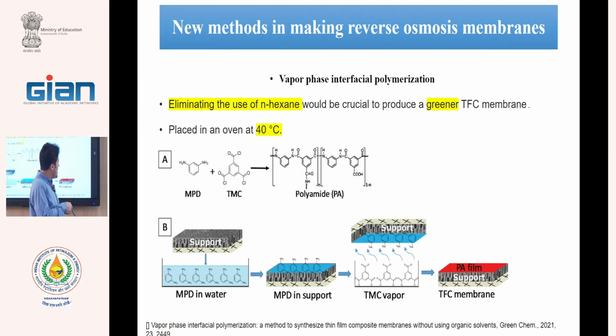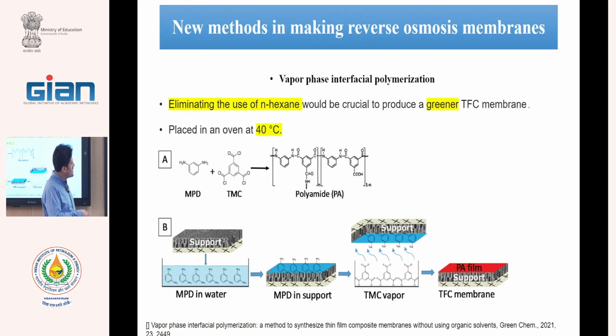The first step is similar. We immerse the support in the MPD aqueous solution and remove the excess with a roller, and in the second step, we do not immerse it in hexane. We put the membranes in a chamber that has a vapor of TMC. We heat the TMC, change it to vapor, and in the vapor phase, it reacts with these amine groups. In this case, the use of hexane will be reduced. We have a greener method.